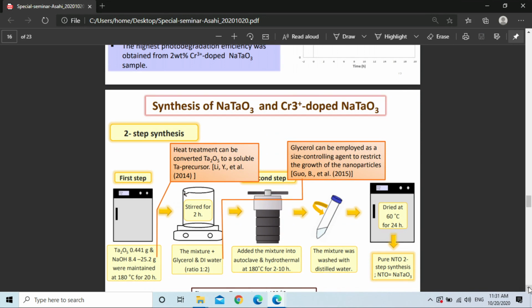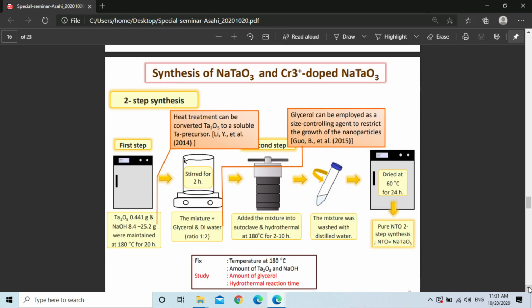But when we tested for hydrogen production, we did not succeed in getting any hydrogen from this material. So we turned to consider the morphology, improving the size and morphology of the material by changing the synthesis. We call it two-step synthesis, adding one step before hydrothermal by treating the starting materials. Just mix the powder and keep it in an oven. We think the heat treatment can convert tantalum to a soluble tantalate precursor and help crystallization in the hydrothermal step.